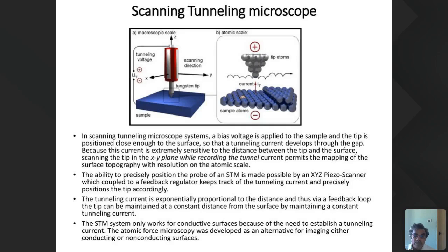The ability to precisely position the probe on the STM is made possible by an XYZ piezo scanner, which, coupled to a feedback regulator, keeps track of the tunneling current and precisely positions the tip accordingly. The tunneling current is exponentially proportional to the distance, and thus, by a feedback loop, the tip can be maintained at constant distance from the surface by maintaining a constant tunneling current. The STM system only works for conductive surfaces, because a tunneling current needs a conductive sample.